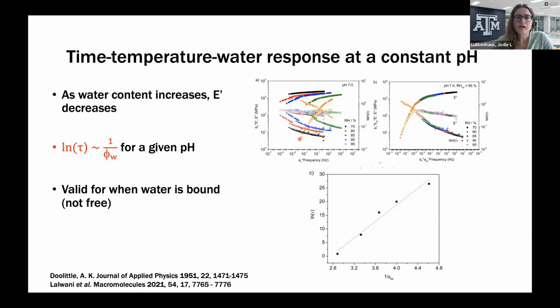We know the amount of water at each of these relative humidities inside the complex, which we can convert to a volume fraction of water. And we plotted that the natural log of the complex's relaxation time varies linearly with 1 over the volume fraction of water in the complex. And so no adjustable parameters, but we see this very robust linear relationship. In this case, for all of these complexes, the water, we know from other DSC experiments, the water is tightly bound in the complex. It's not free water. So in this case, we know all of our water is interacting with charge groups. So this seems to hold very well for that.